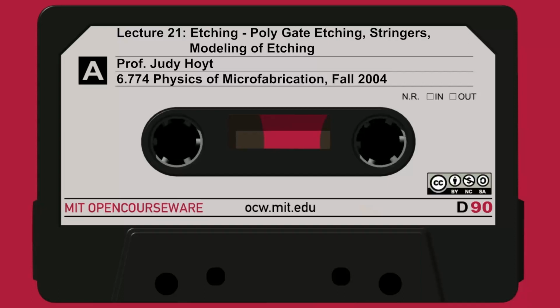Okay, so that's one example. If I move on to slide 6, we not only have to etch silicon into the single crystal material, but we also have to etch silicon when we're etching the gate. And in fact, etching the gate is becoming more and more complicated. This is an example on slide 6 of etching what we call a compound gate, or a gate that already has a gate stack or already has several materials that it consists of.